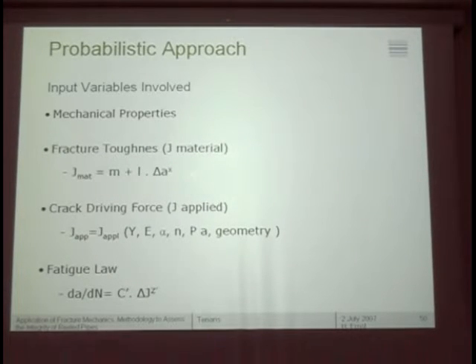Just for you to remember, what we are doing is using the material resistance curve. I go back to J, but of course we can put that in terms of the CTOD, using the standards, which means that you can fit your experimental data with 3 parameters, M, L, and X. Sometimes you use 2 only, depends on what you want, but you can do both. The crack driving force, which we can also put in terms of CTOD, is proportional to the yield, the Young modulus, the parameters alpha, n, and so on, the load, the geometry, and so on, and the